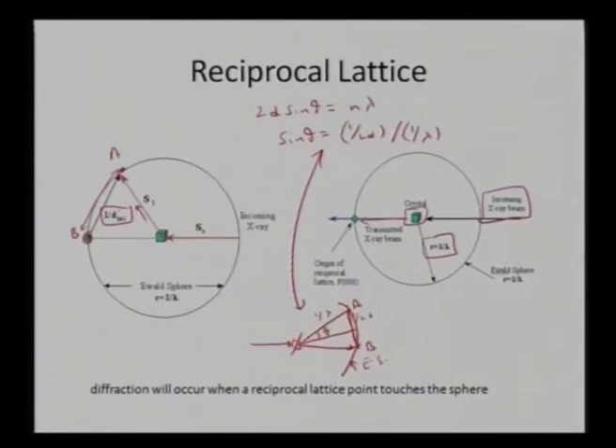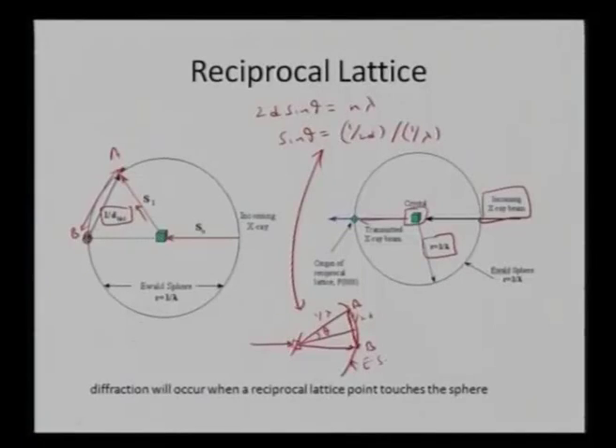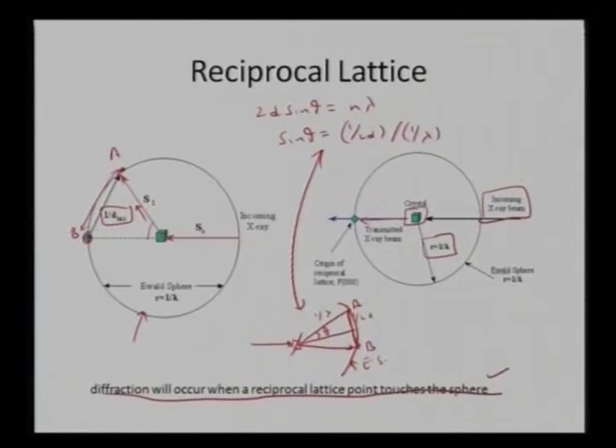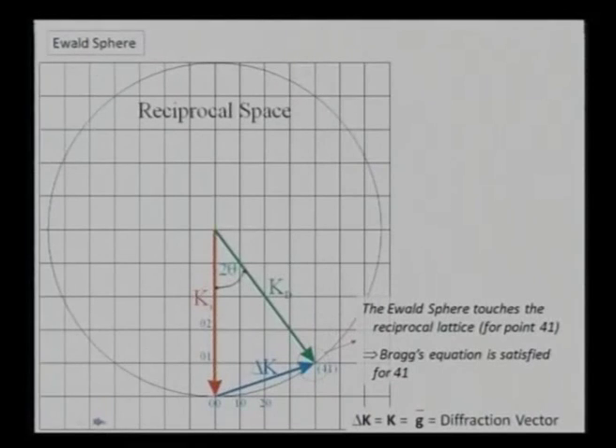The spacing of 1/d is what is being represented by the reciprocal lattice. All points on the Ewald sphere — all reciprocal lattice points falling on the Ewald sphere — are producing my diffraction spot because they are obeying Bragg's law. So sin θ = (1/2d)/(1/λ); the Ewald sphere has radius 1/λ, 2θ gives 1/d, and that is what gives me the diffraction spot. Diffraction occurs only when a reciprocal lattice point touches the Ewald sphere.